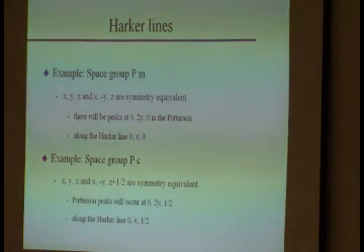Well, x minus x in vector space, that's 0. y minus minus y, that's 2y. And z minus z, which is 0 again. So the interatomic distances between equivalent atoms will be 0, 2y, 0, where y is the coordinate of each individual atom.